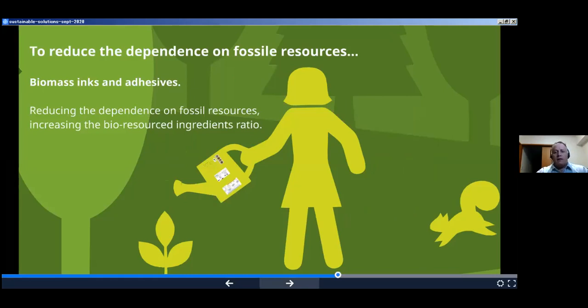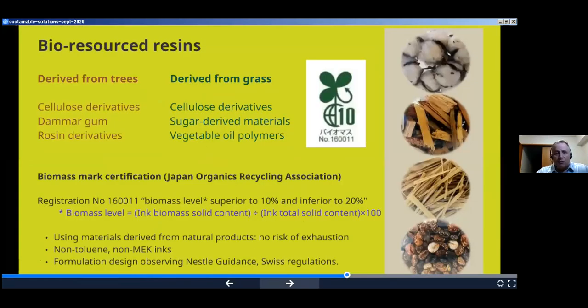Another thing is how we can reduce the dependence on fossil resources. In our case, we are suggesting, and we are already selling in Japan, the biomass-based inks. So we have inks where we substitute part of the fossil resin in the ink with biomass resin. Depending on the amount of biomass contained in the ink, the ink can be labeled as 10, 20, 30, 40%, etc. And these are the inks that we are developing. We have inks for all the printing processes, like offset, gravure, flexo, for surface, for reverse printing, etc. And we also have lamination adhesives that contain biomass material in order to reduce the consumption of fossil resources.